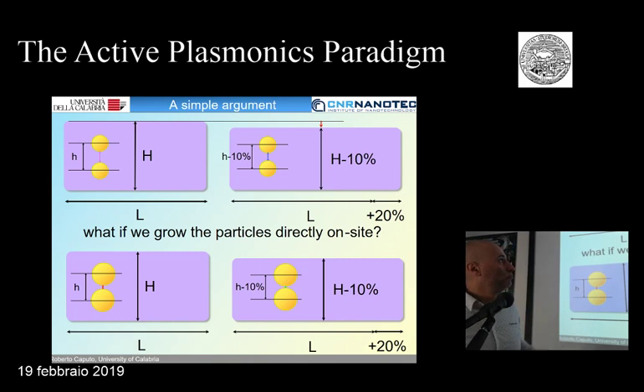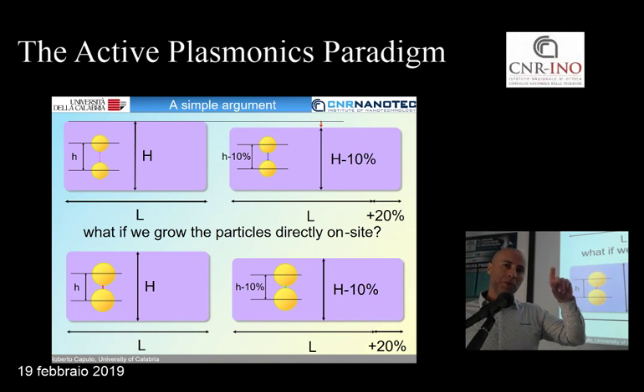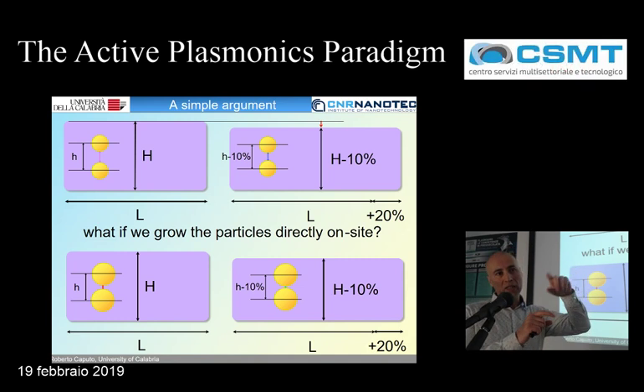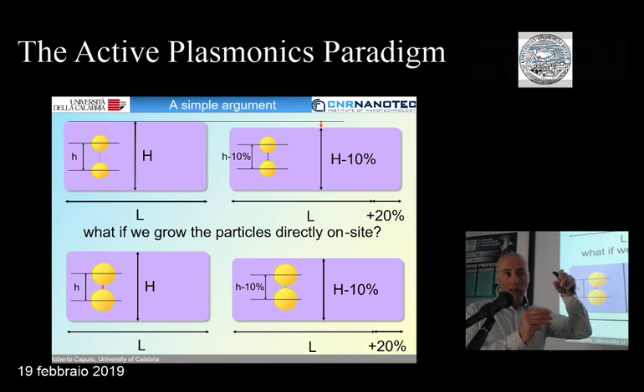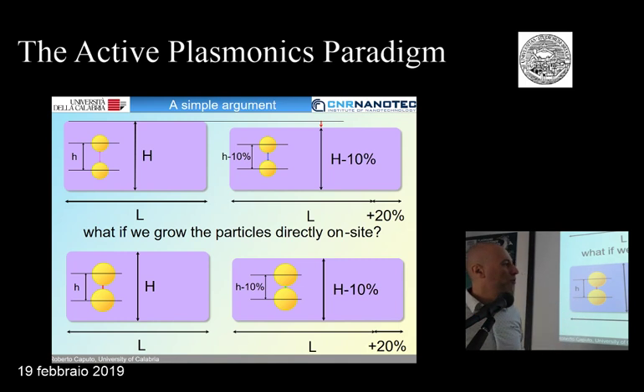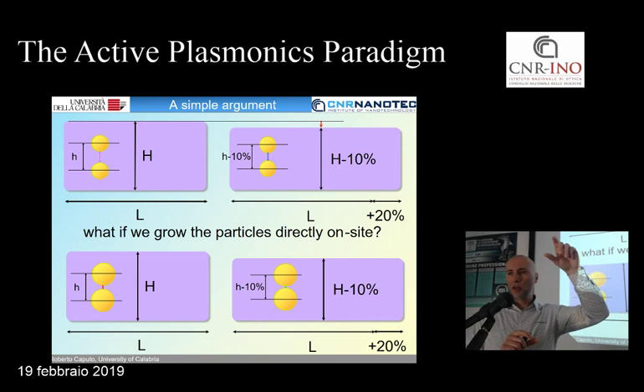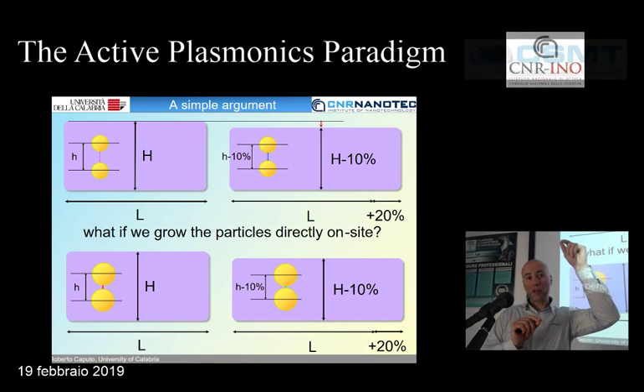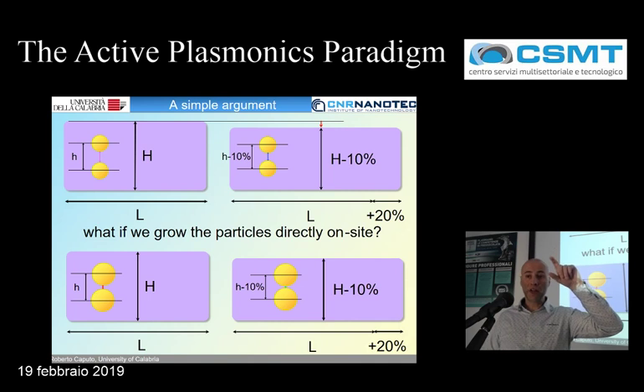So the point was that if you bring the particles to a close distance, you have a plasmonic coupling, as I said before. You have some overlap of the electronic clouds of the particles, which generates a redshift of the plasmonic resonance. And you can control this distance by just elongating the substrate. So it's very easy to do. The only problem was that if your particles start from a very large distance, even if you apply your elongation and consequent compression, they don't go very close to each other.